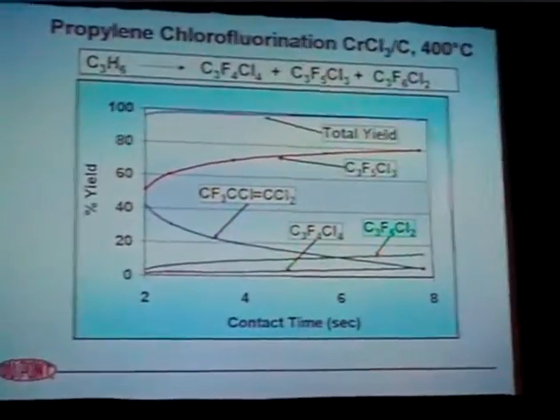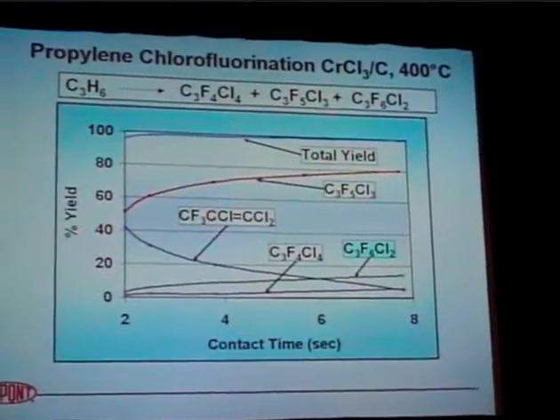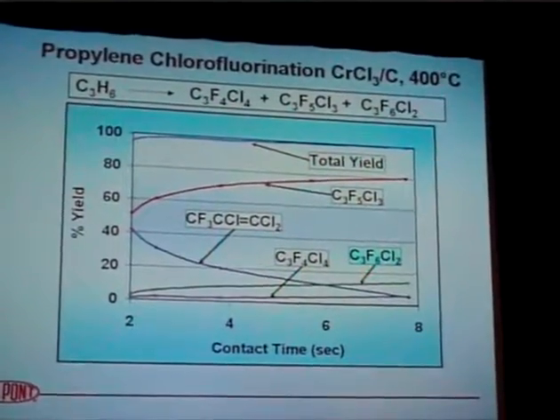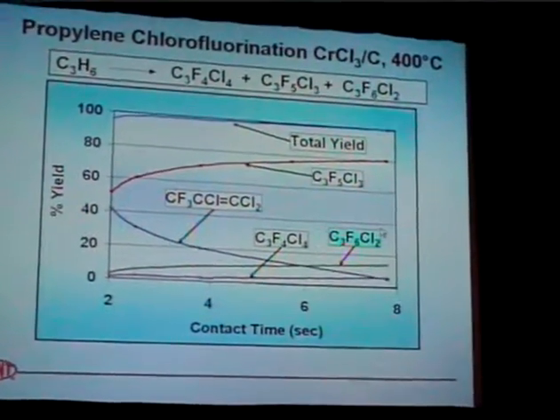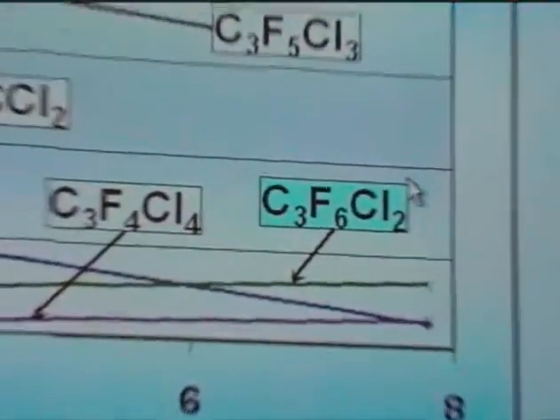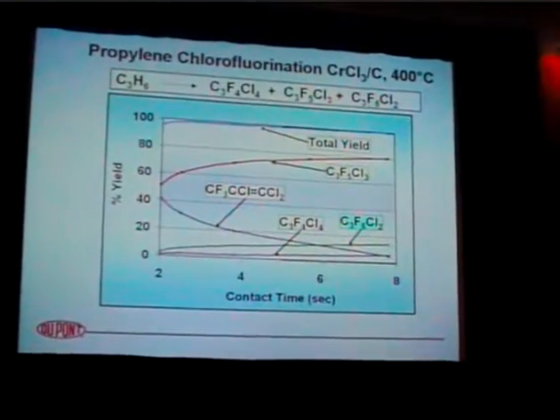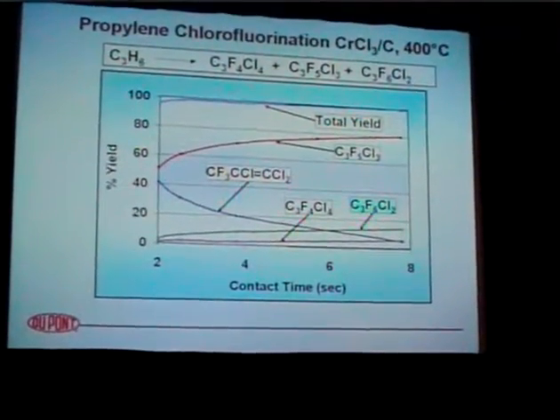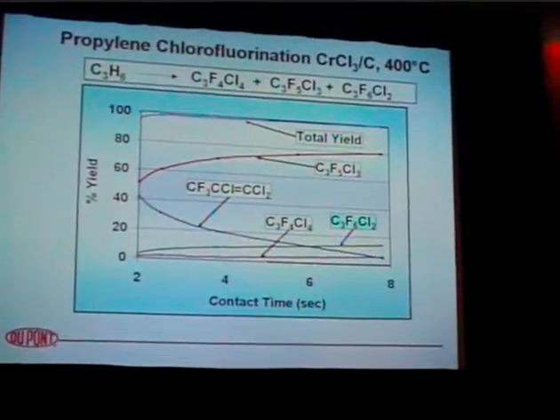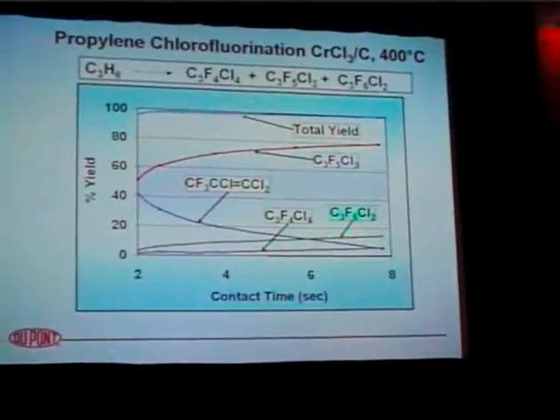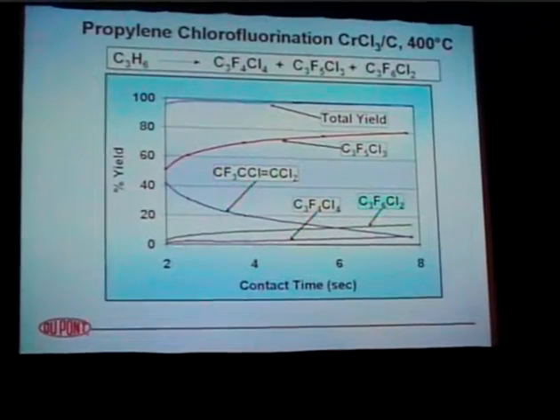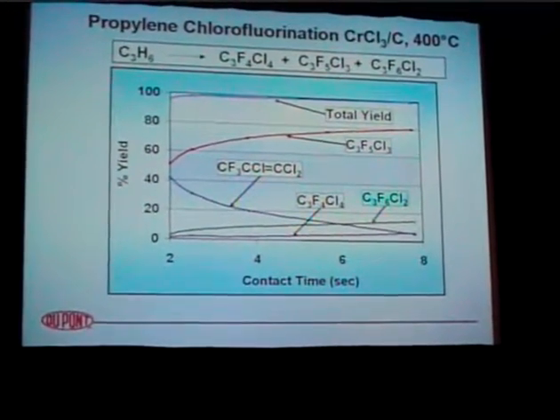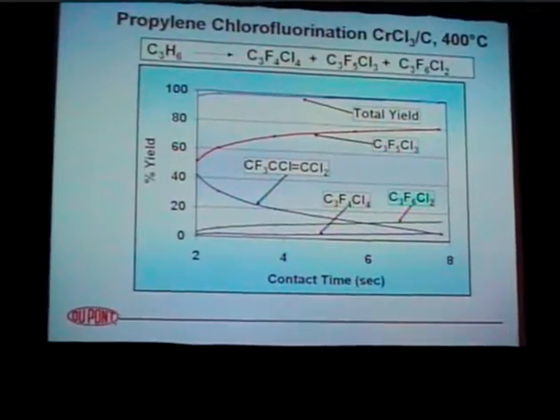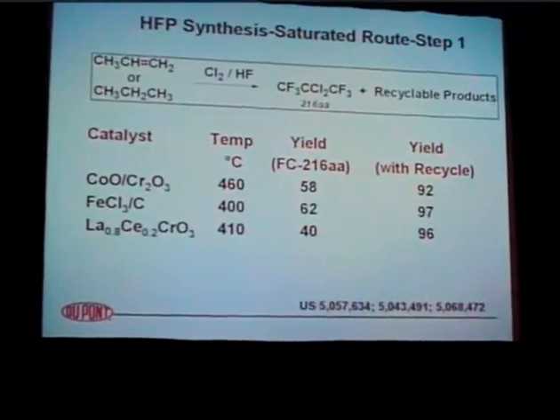But if you look at it, you'll find that the major product that we're interested in is the one down here, if you can see it, in the bottom right-hand corner, the dichlorohexafluoropropane. That's where we want to go. But all of those other materials that you initially make on the GC are all precursors. They can all be very easily recovered and recycled back through the process to give us the overall 99 or so percent yield that you can achieve in this reaction. So I'll show you a little more detail on the next slide.